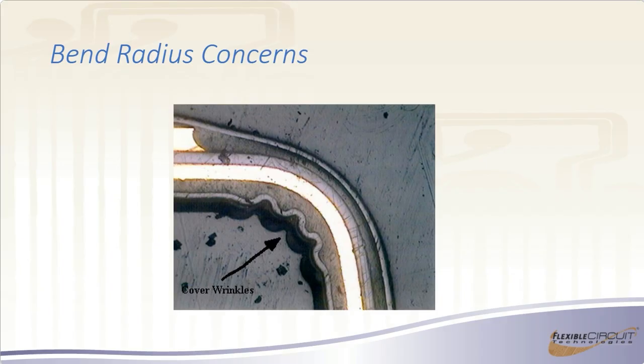This is what happens when you have excessive compression forces. Here you can see that we have heavy copper and a thick layer of polyimide, and so we end up with this rippling in this area. And this by itself isn't a problem. You can see that where the adhesive is, you have a full bond there, there's no laminate voids, and so this by itself is not rejectable. If I was seeing delamination occurring in the area where you're seeing that puckering, that would be a problem. But if everything holds up, this is fine.